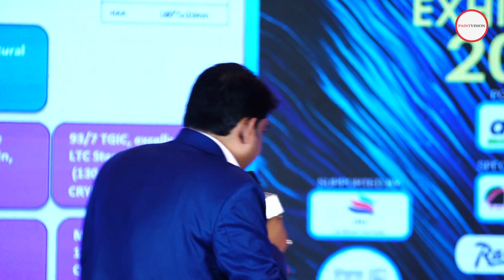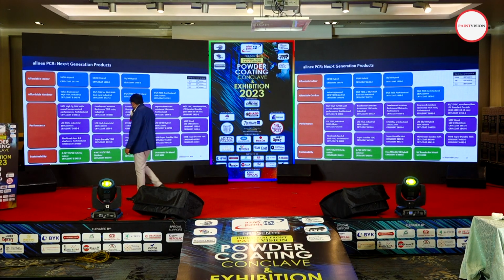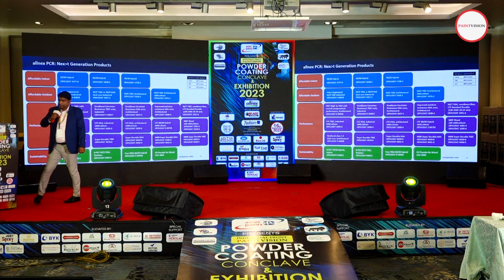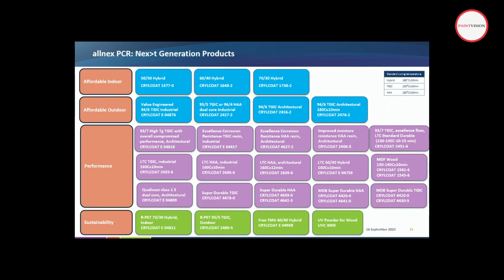And if we are talking about, again, the low temperature cure, standard formulation, standard performance, and with excellent flow, we have 93.7 TGIC, which cures at 130 to 150 degrees centigrade within 10 to 15 minutes, and that is Crylcoat E2451-6. Then we are talking about the industrial segment, LTC TGIC system, it is 160 10 minute, 2435-6.